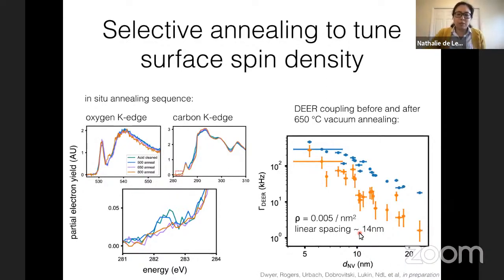So in that regime, you would not expect to see this kind of nice monotonic scaling, but you should instead see some increased variance as you go closer to the surface, because you should accidentally be really close to some surface spins and occasionally very far away from some surface spins. Okay, so that's the first big puzzle.